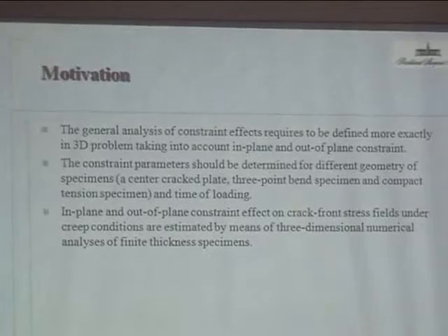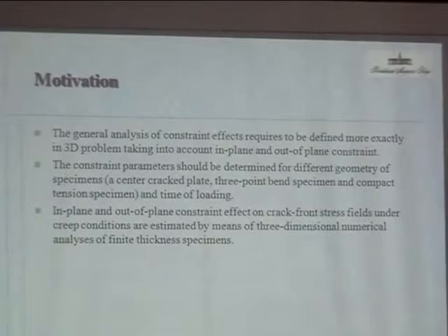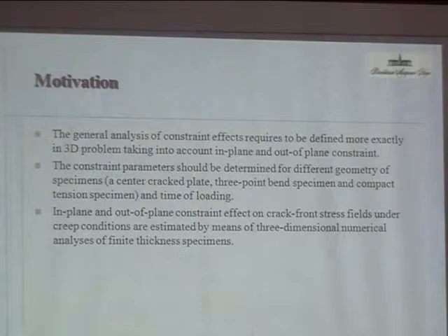But if we consider a three-dimensional crack problem, in this case, we need to take into account two parameters connected with the constraint. The first one is associated with in-plane constraint, and the second one, T33, is an out-of-plane parameter. So we need to take into account this parameter to construct some constraint-corrected fracture mechanics approach.